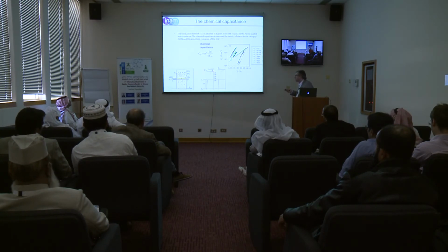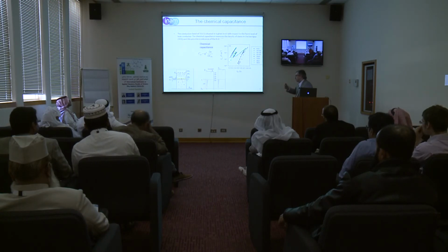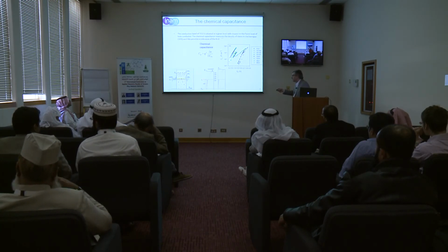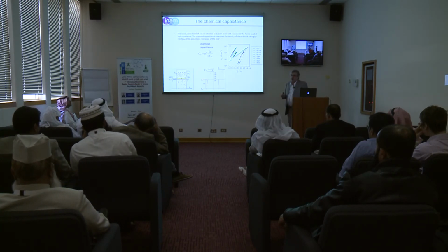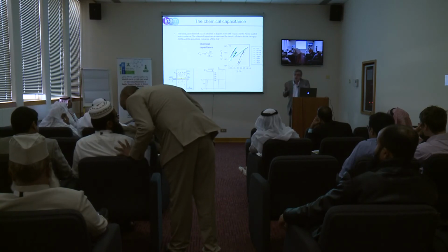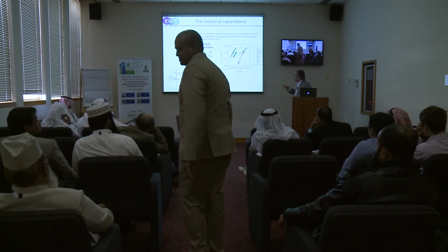It's an exponential distribution, so that when you move the voltage in your contact, what you're moving is the position of the Fermi level, so you are filling the density of states. So really by a scan of voltage, you can see the density of states, and this you can do by cyclic voltammetry, or you can do it by impedance spectroscopy, like I show here.